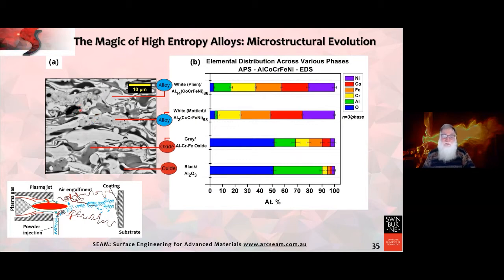And after a great deal of microscopy and X-ray diffraction and very careful thought, Amy was able to distinguish various phases of different constituents within a high entropy alloy, all arising, and this is just to remind me, all arising due to these features that happen within the thermal spray torch. So depending on where the particles and the size of the particles and the alloy constituent, you either get this phase, this phase, this phase, or an oxide.